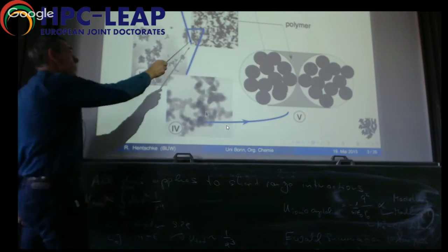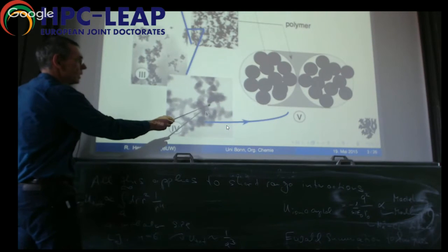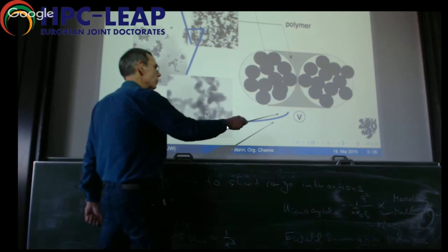And this is because what happens is that when you pull on this stuff, the little contacts here between these balls, which you see here as dark circles, are broken. So there are little cracks appearing in the material, and that weakens the material and diminishes the spring constant. And this is what we have tried to model here.